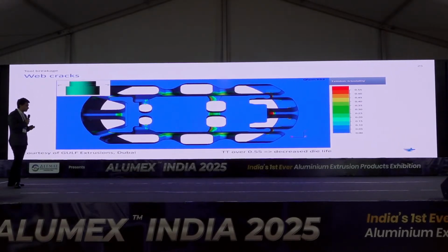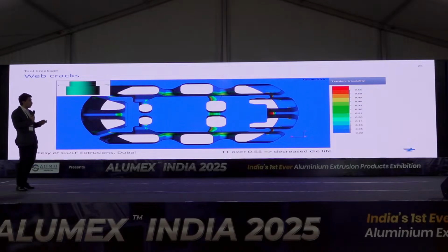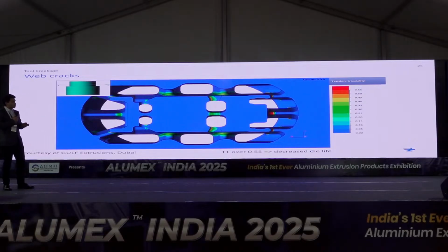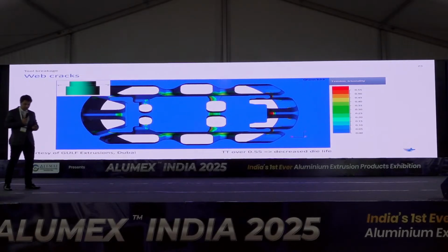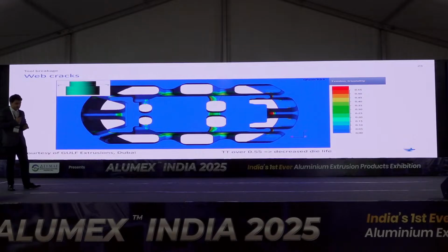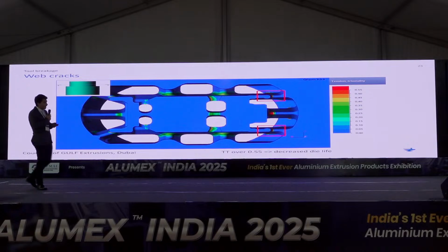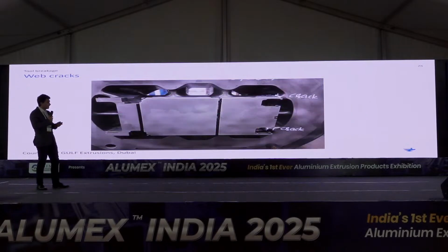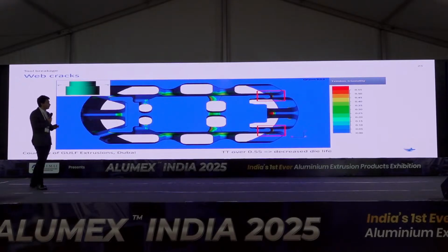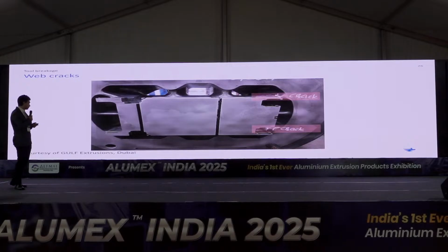Another approach is to check the stress state under the webs, because you can expect crack appearance not only on the console parts of tongues because of a high tongue ratio, but also under the webs. Very common. Unfortunately, here almost every time we can have some plastic deformation under the webs because of very high tensile stresses. We have a special criterion, and once some critical value of the criterion is achieved, using some post-processor analysis, we can find these areas and say that there will be cracks. This matches exactly the results that you can see in this photo.